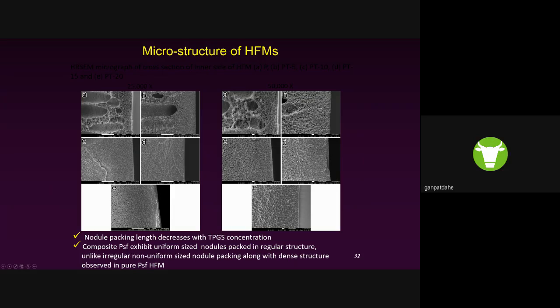And these are the nodules made from the polymer. It's very difficult to know how much TPGS is in the nodules. We haven't done those studies, but we did ATR studies, and from that we confirmed the presence of the TPGS. So this is a really good result that we obtained.